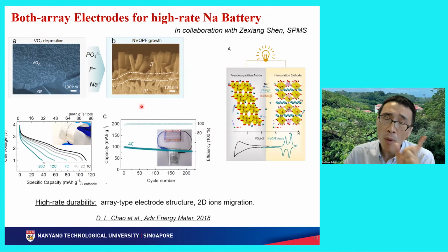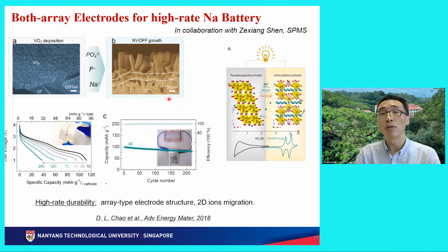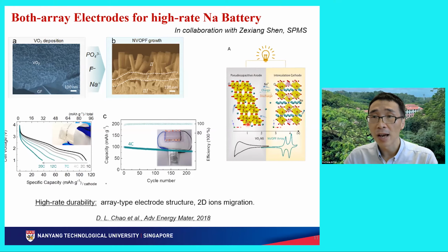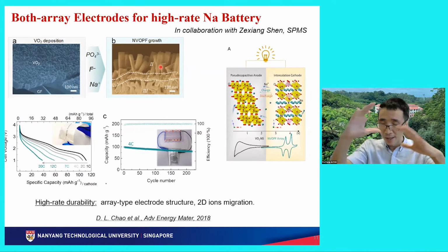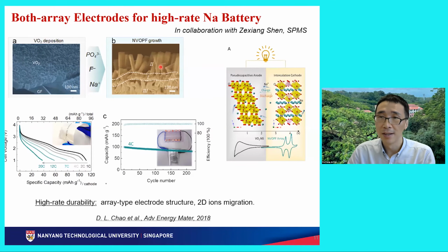The reason we can achieve high rate fast charging and discharging is the different electrode and battery architecture compared to commercial powders. On the anode side is a pseudo-capacitive anode. On the cathode side is an intercalation cathode, but it also gives very high rate performance because of the three-dimensional graphite foam current collectors. When we put them together to form a rocking chair sodium battery, we find that both can give very high capacitive behavior, which you can see here, giving the high rate performance.